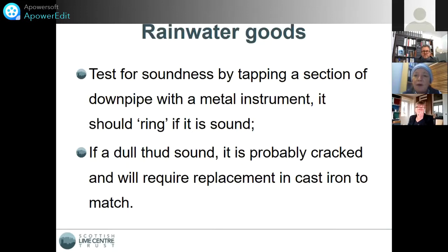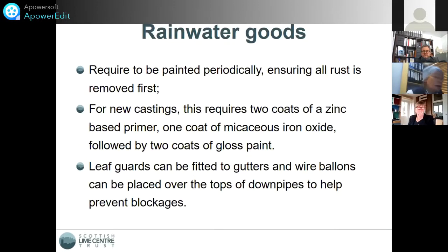You can test for the soundness of cast iron rainwater goods by tapping a section of a downpipe with a metal instrument, and it should ring if it's sound, but if you hear a dull thud, it's probably cracked and will require replacement in cast iron to match. And of course, cast iron rainwater goods require to be painted periodically, ensuring all the rust is removed first. If you have new castings in replacement for cracked downpipes or gutters, for example, they should have 2 coats of a zinc-based primer applied, then a coat of micaceous iron oxide, followed by 2 coats of gloss paint. As I mentioned earlier, leaf guards can be fitted to gutters and wire balloons can be placed over the tops of downpipes to help prevent blockages.